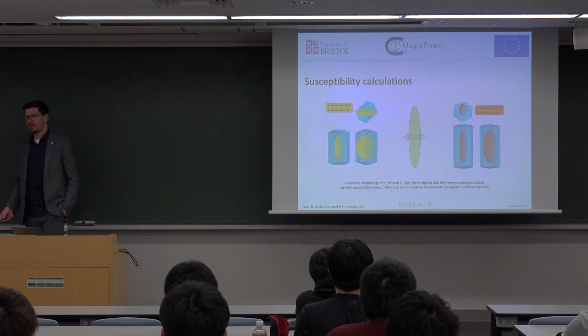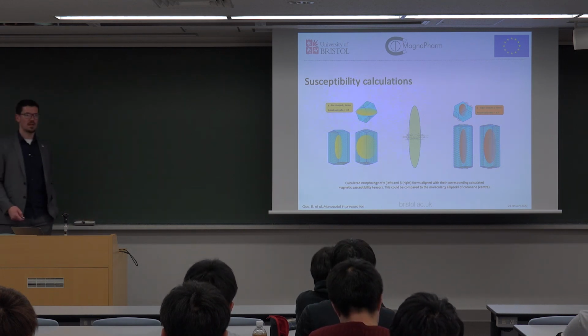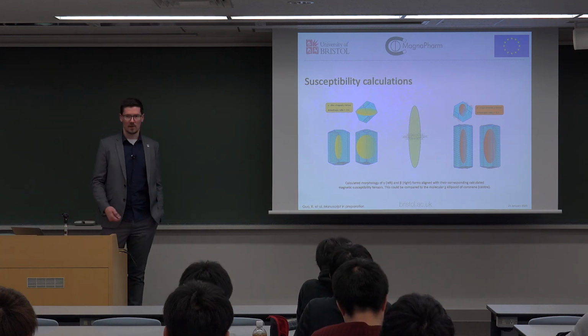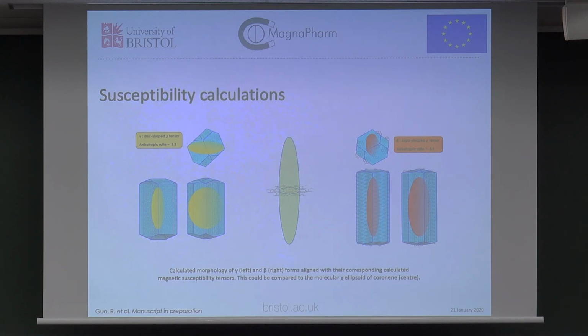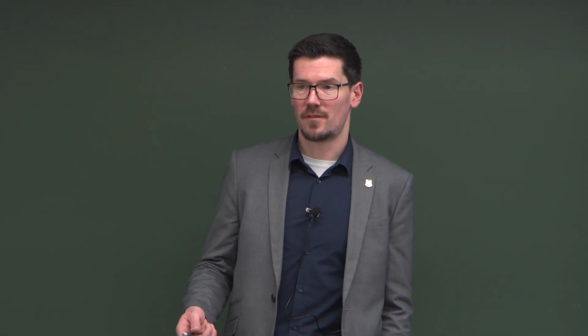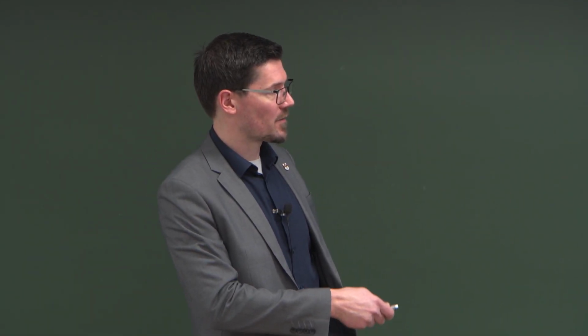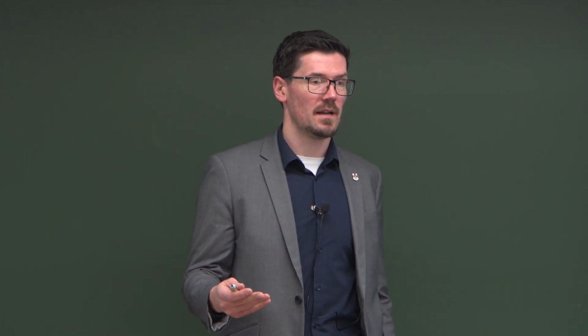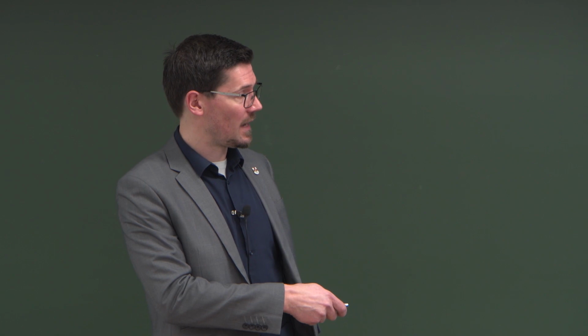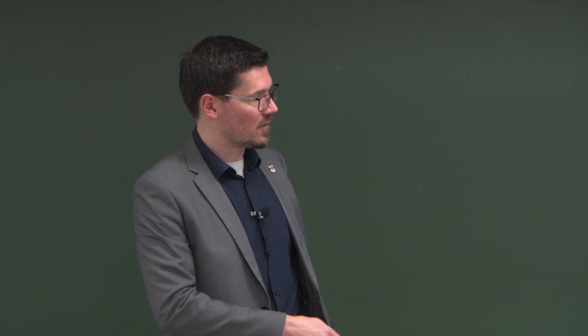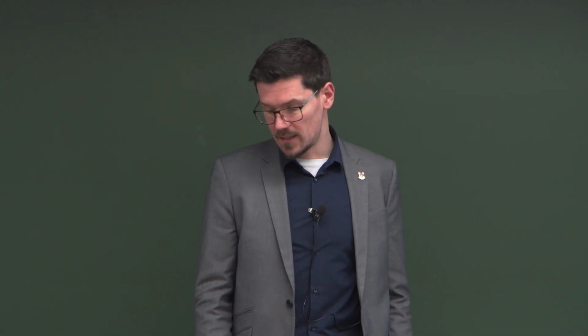So another new method that's been developed at UCL, Rui has developed a way to calculate the magnetic susceptibility of a unit cell based on where these molecules are positioned. So what you're looking at here is the ellipsoid that is indicating the magnitude of the anisotropy of the magnetic susceptibility. So if it's here on the single molecule, that means that if you were to put the magnetic field going across the plane of the molecule, it wouldn't be that energetically unfavorable. However, if you turn the magnetic field so it's going through the molecule, suddenly there's a greater susceptibility on that molecule. So what you're seeing here is gamma on the left, beta on the right, and you can see the ellipsoids for beta coronene are a lot greater, implying a greater magnetic susceptibility.